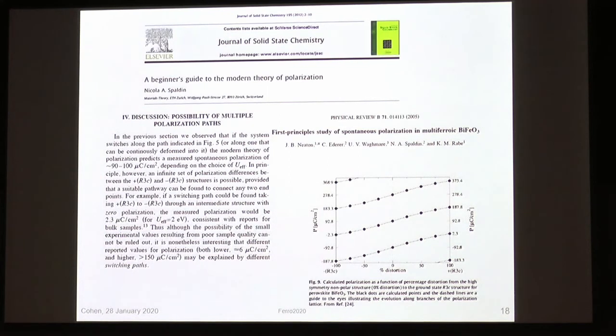If we choose, you notice here, this is one of these cases where zero did not give zero. So zero distortion, this is like cubic perovskite, does not give zero in any of their calculations. Instead, it's plus or minus this half a quantum. So when they map out the actual polarization and compare with experiment, they take this number here and subtract this number for zero, and they call the difference the polarization.